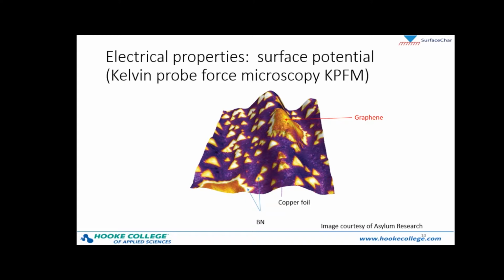KPFM maps the variation in contact potential between the tip and sample, which can be converted to the work function difference between the probe and sample. It is also referred to as surface potential or work function imaging. Applications of this method are diverse and include corrosion studies, photovoltaic effects in solar cells, and catalytic activity. It is another example of this mode that gives us sensitivity or contrast based on the electrical properties of the sample. In this case, its work function.